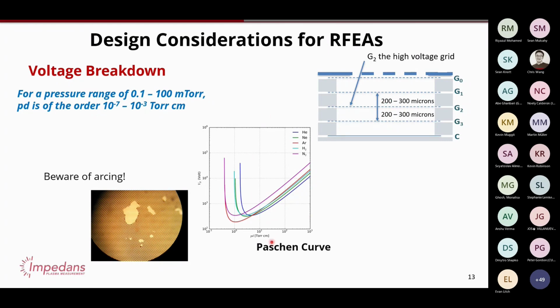You look into what's called the Paschen curve. The Paschen curve is basically, on the x-axis, the pressure times the distance, and on the y-axis the breakdown voltage. And here are curves for different gases. You can see here, for example, argon has the lowest breakdown voltage in a certain range. So argon plasmas are very easy to strike. Whereas something like helium requires a much larger breakdown voltage, and the ideal situation is at a higher pressure than argon, or a different electrode separation. So these are harder to strike.